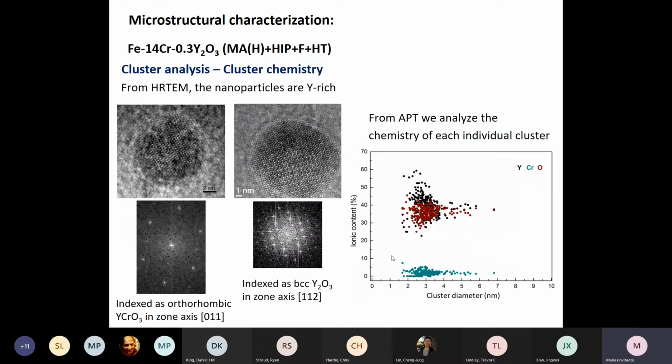Okay, and also, in atom probe tomography, except in very specific and very favorable cases, we cannot get an idea of the crystallography of the nanoparticles, or at least I couldn't in my experience. So we can combine the information that we can get from TEM by diffraction.